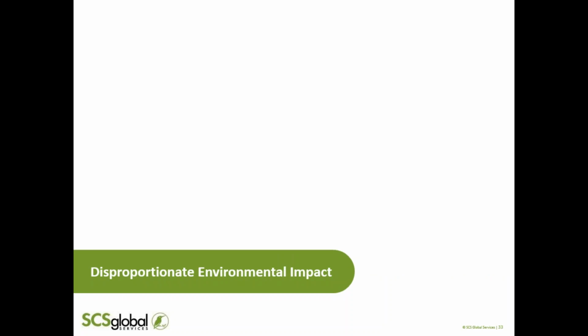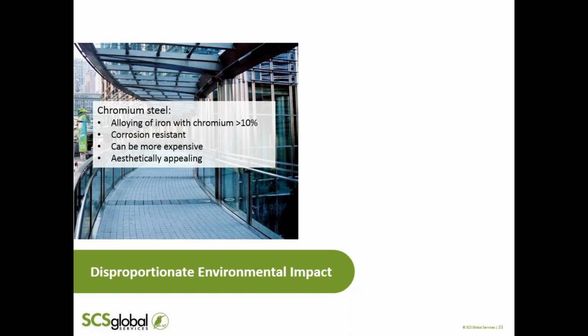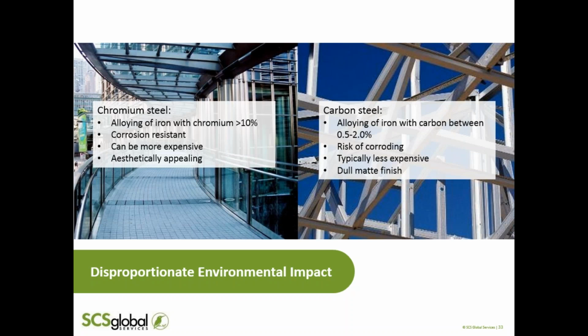Processes that have the largest contribution to environmental impact for one product may not be the case for another in the same product category. This can be seen for some steel products. Consider chromium steel versus carbon steel. Chromium steel is made from iron alloyed mainly with chromium at a percentage typically greater than 10%. It is a corrosion-resistant product and is typically more expensive than carbon steel. Carbon steel is made by alloying iron with an amount of carbon between 0.5 and 2%. Unlike chromium steel, it runs the risk of corroding and is typically less expensive.